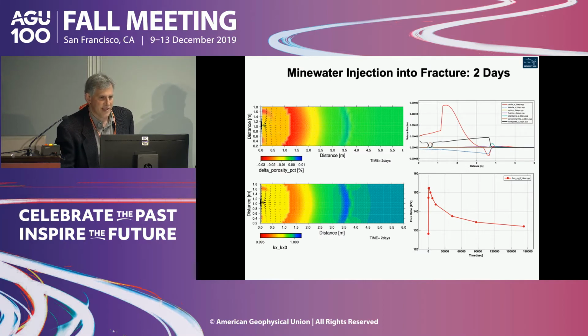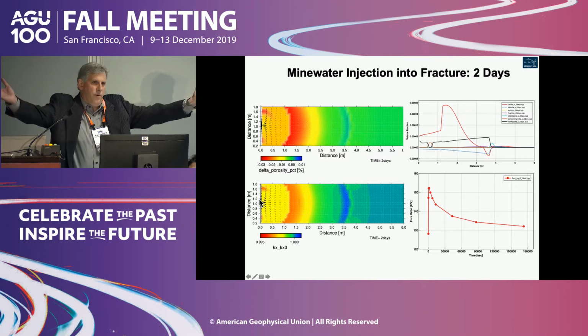And then other things, the porosity. You know, after 2 days, we don't get a lot of change, but we're starting to get like a few % change in porosity out in this band here, decrease in porosity, and small increases out in this front where it's more acidic and you're dissolving. And you can see this jumping up here. That's calcite precipitation in this region, and some of the other minerals in lesser abundances. And one thing you see with the flux, these are the flow vectors, the flux ratio of X to Y, it actually increases, which means that you're basically starting to plug around the inlet and you're pushing the water out to the sides.